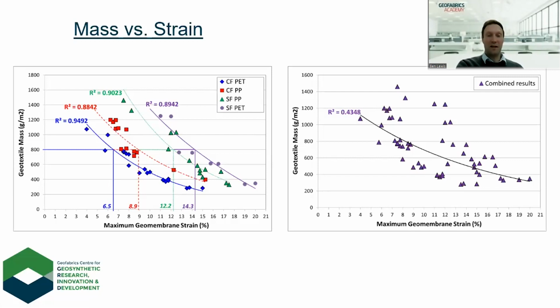You really need to look at how the product is manufactured, and it was quite clear that continuous filament polyester geotextiles perform far better than anything else. This plot on the right is just basically a curve plotted through all the same plots without considering anything else, just really looking at mass versus maximum strain. And really the correlation is quite poor. It's 0.4 versus around 0.9 when you start to consider the actual manufacturing process.